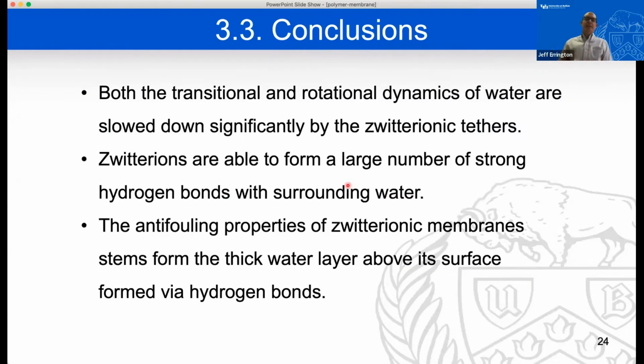So what all of these suggest is they're consistent in terms of what they're telling us, and that the translational, the rotational dynamics of water in the vicinity of the polymer tethers is slowing. And it also tells us that the Zwitterionic tethers have a more significant impact on the mobility of water than those of the non-Zwitterionic polymers.